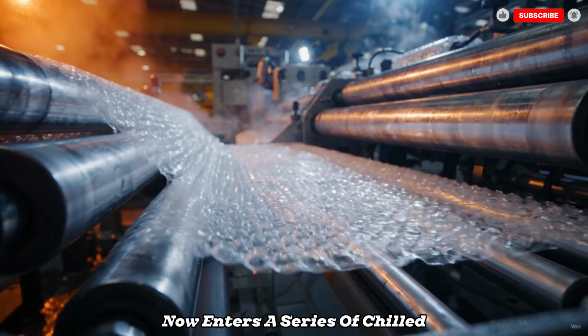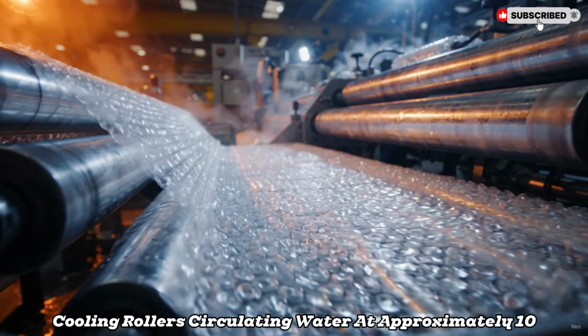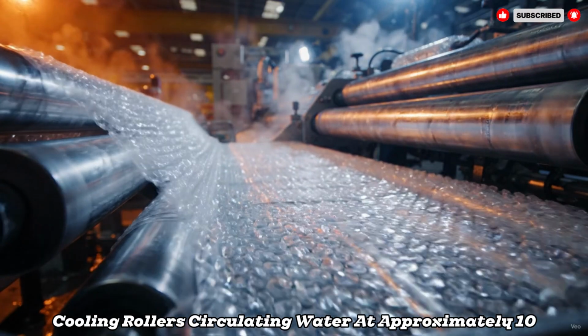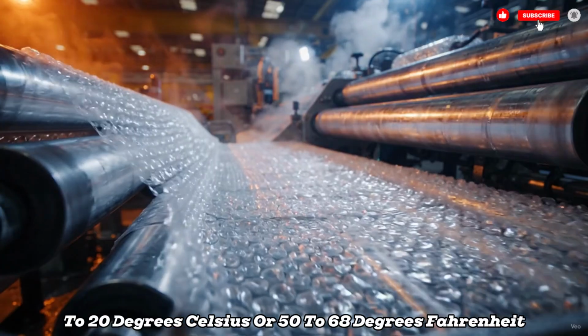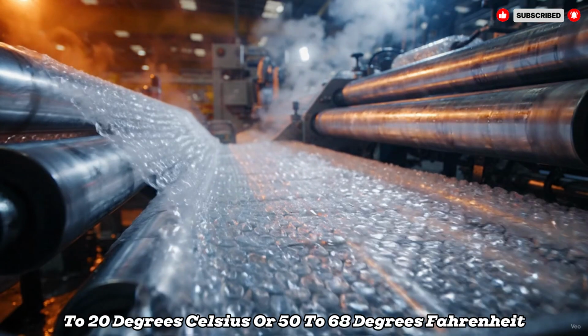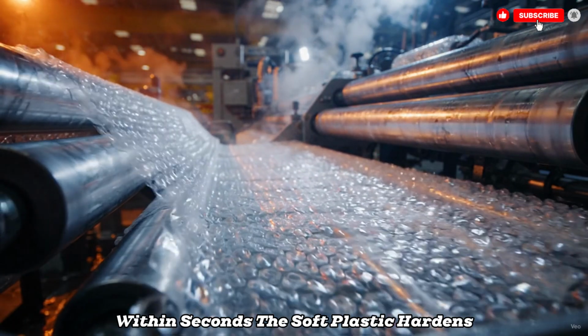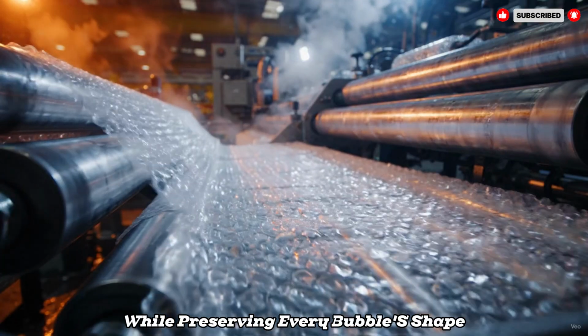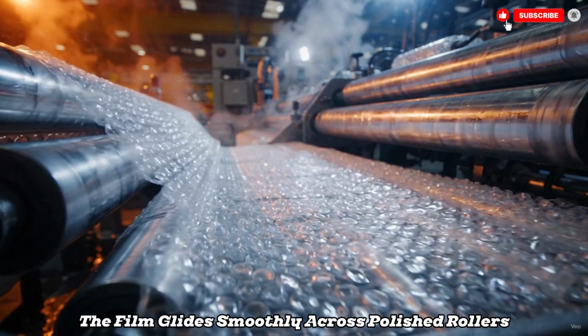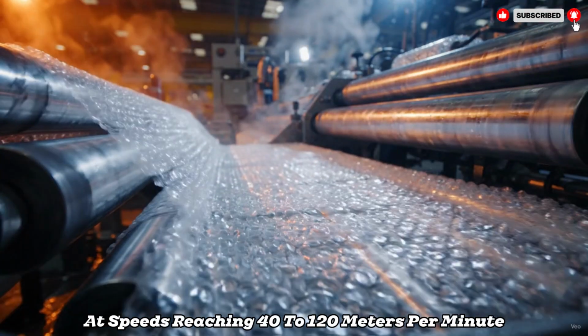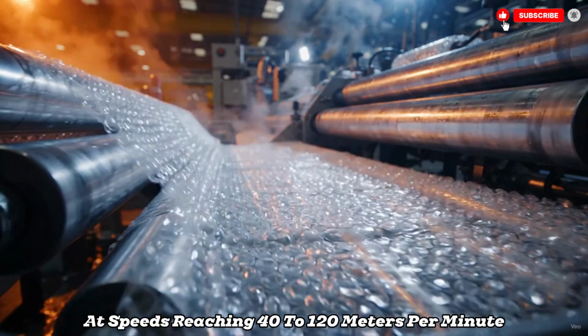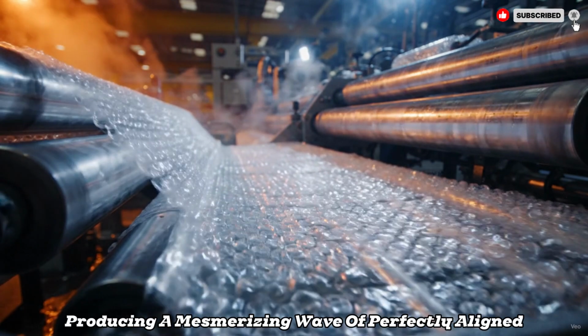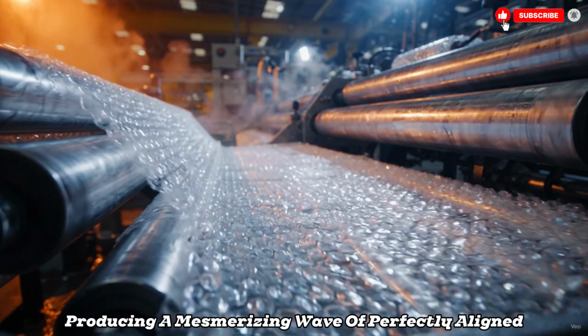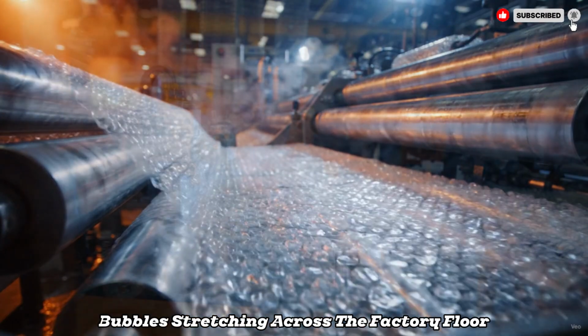Freshly sealed bubble wrap now enters a series of chilled cooling rollers, circulating water at approximately 10 to 20 degrees Celsius, or 50 to 68 degrees Fahrenheit. Within seconds, the soft plastic hardens while preserving every bubble's shape. The film glides smoothly across polished rollers at speeds reaching 40 to 120 meters per minute, producing a mesmerizing wave of perfectly aligned bubbles stretching across the factory floor.